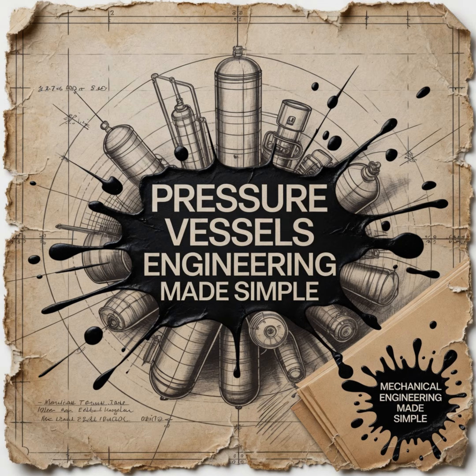This is where we run into what the sources call shop floor sins. Ooh, shop floor sins. I like that. The correct, tedious way to fix an out-of-round shell is to re-roll it, or carefully apply localized heat shrinking. Which takes time. A lot of time. The fast, dangerous way is to force the fit. Forcing it. The fitters will weld massive steel cleats to the shell and the head, hook up 10-ton hydraulic jacks and chainfalls, and literally crush, push, and stretch the steel until the edges align. Just brute force. Pure brute force.